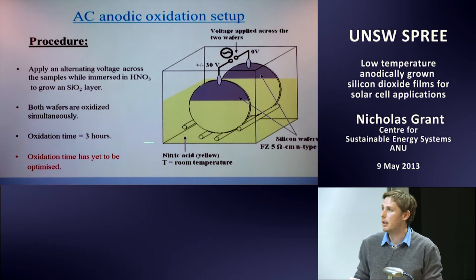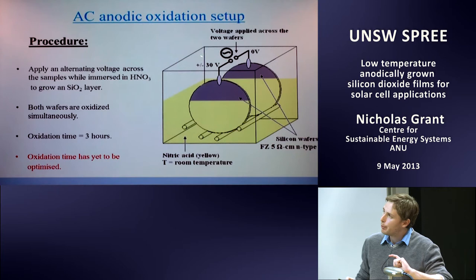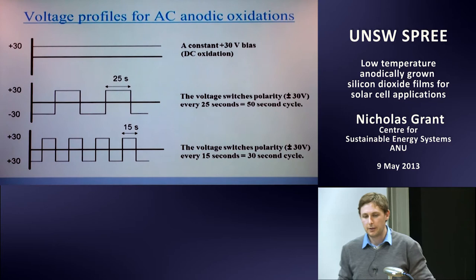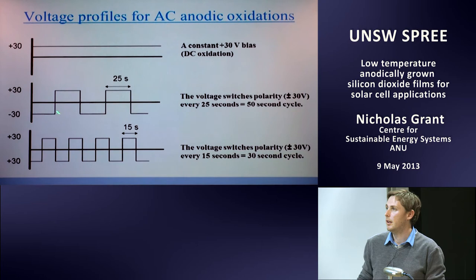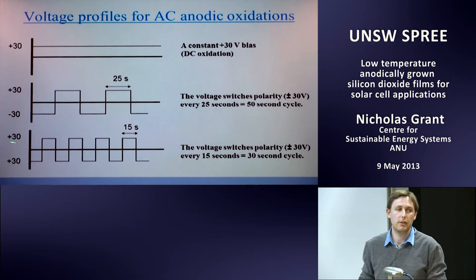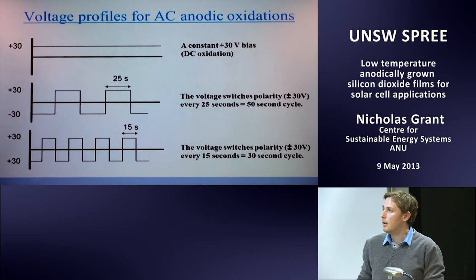The AC oxidation is carried out for three hours in nitric acid. One electrode is flipped from minus 30 to plus 30 volts — when at plus 30 volts one electrode oxidizes, and when at minus 30 the other electrode oxidizes. We investigated cycle times of 20, 30, and 50 seconds, maintaining a constant voltage of plus or minus 30 volts. The lowest half-cycle time investigated was 15 seconds.